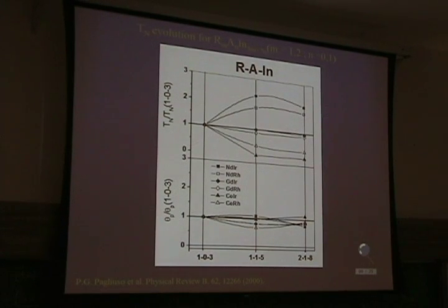Okay, so another way to look at the evolution of the Néel temperature is comparing your Néel temperature for the tetragonal compounds with the cubic ones. So what changes when you make it more tetragonal? First, you get your susceptibility data, make a polycrystalline average, and look at the high temperature. You can calculate your Curie-Weiss temperature, right?